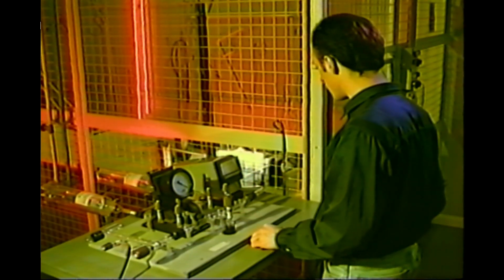If the gas discharge color deteriorates due to contamination, a second bombardment can be performed using the helium gas in the tubes. To do this, increase the current to between 700 and 900 milliamps and effect full heating of the tubes once more to 250 degrees centigrade. Then repeat the rinsing process to assess the results.